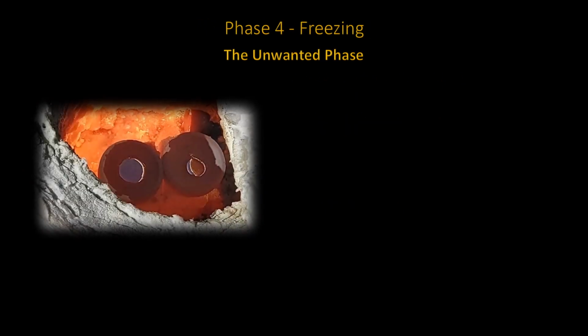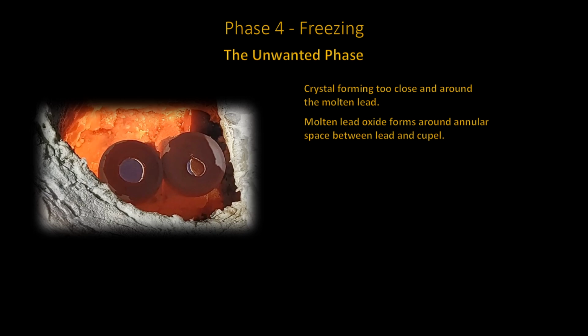During phase 3, things can and sometimes do go sour. This could become phase 4. That is, the temperature of the Cupel drops and it is unable to absorb the litharge. If crystals of lead oxide start to form close to the molten lead button, it is an indication that the process is going sour. If the furnace temperature is not increased quickly, this litharge will start to form around the annular space between the molten button and the Cupel.